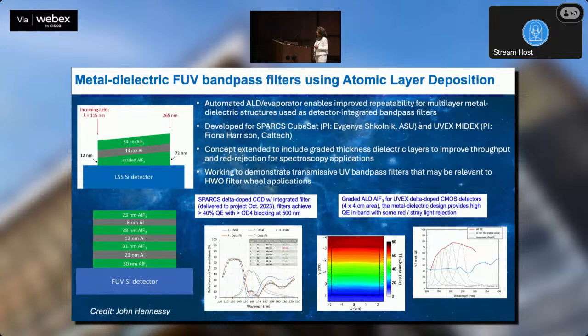The breakthrough that I was talking about, also partially enhanced by or enabled by ALD, is putting metal dielectric filters as an integral part of the detector. So now you can get this detector that was a very strong UV and visible detector and suppress the out of band, or suppress the visible and get a solar blind or visible blind detector. These are two really amazing breakthrough developments with the photon counting, with the solar blindness. And remember, the scalability and manufacturability is still there, reliability is still there. So this is a very exciting development.